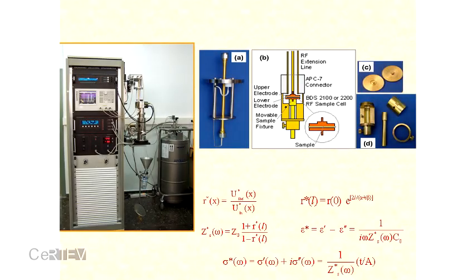Here I have shown this type of measurement, sandwiched between two electrodes, which is possible only for a limited frequency range, up to 100 megahertz. Beyond 100 megahertz, this type of structure is impossible because the resistance of the contact between the materials and the electrode becomes comparable to the resistance of the materials. So we need to measure it without contact, without the help of any contact electrode.